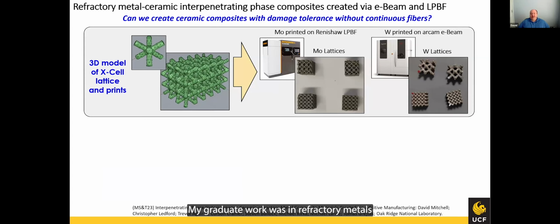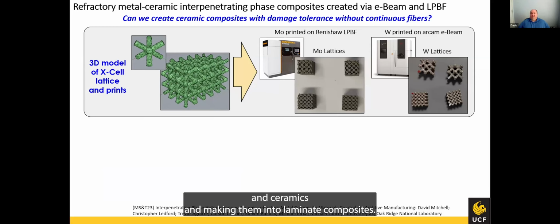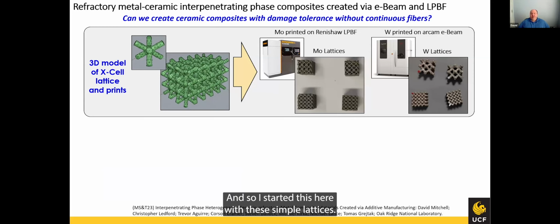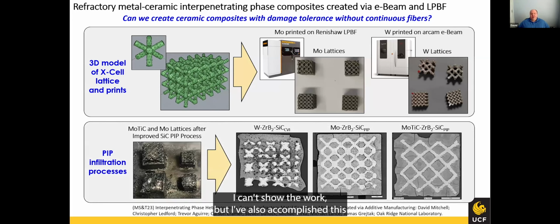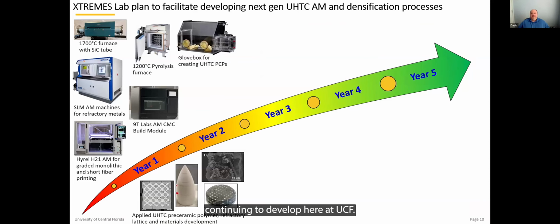My graduate work was in refractory metals and ceramics and making them into laminate composites. But now we have the ability to take those refractory metals and print them into very complex shapes. And so I started this here with these simple lattices. I can't show the work, but I've also accomplished this with more complex lattice structures like a gyroid structure. And so we're seeing good results on mechanical properties. We infiltrated these. Some of them were molybdenum carbide. Some of them were molybdenum. Some of them were tungsten lattices. These were all printed through additive manufacturing and then infiltrated with ceramic processes that we created at Oak Ridge. And these, again, are the infiltration processes we'll be continuing to develop here at UCF.